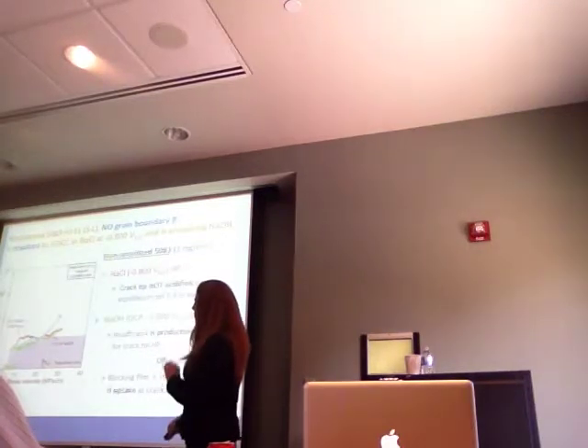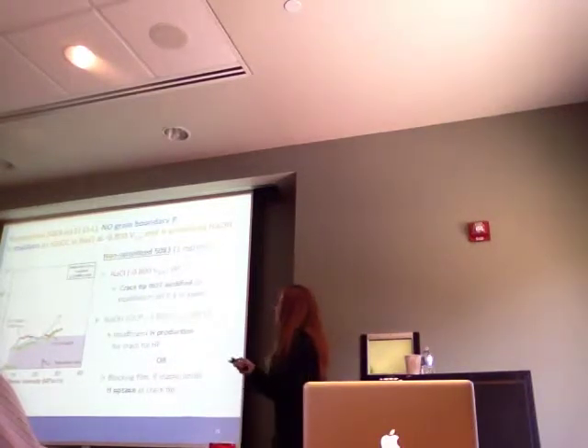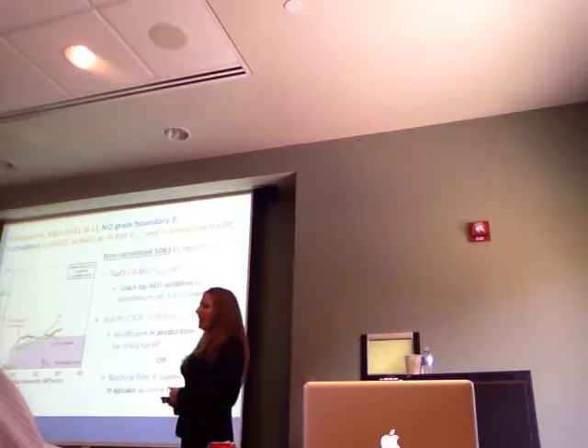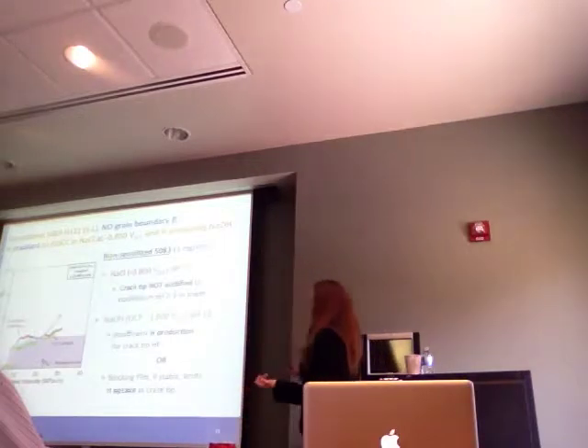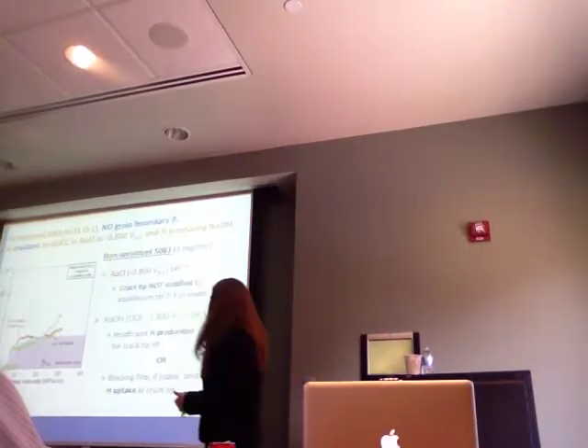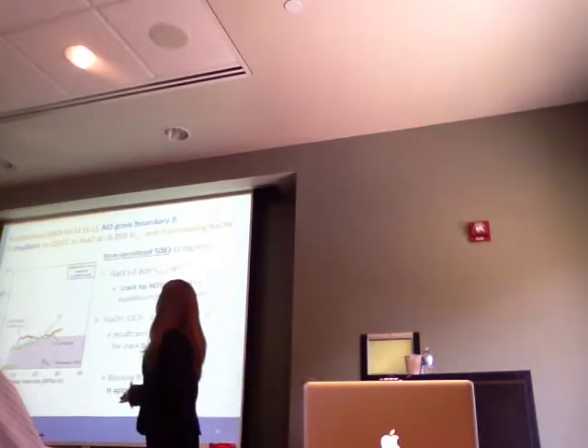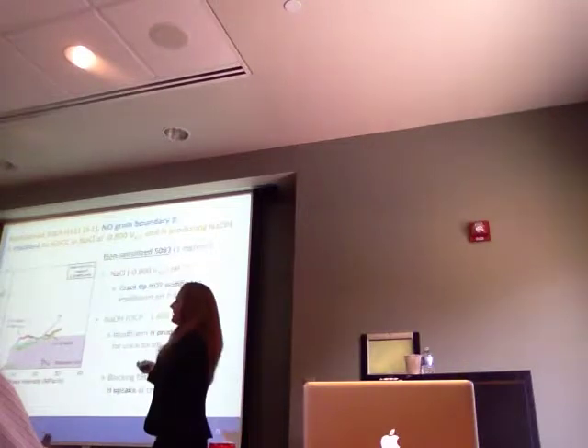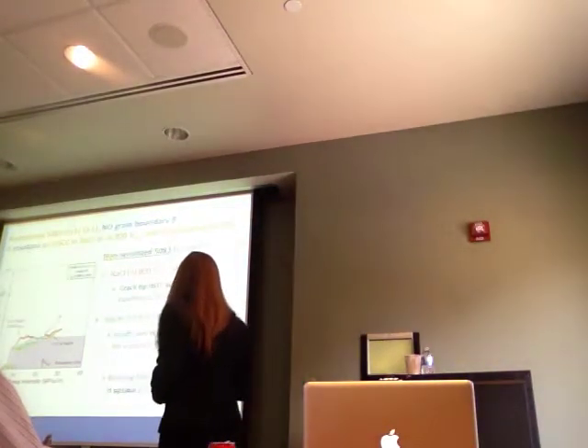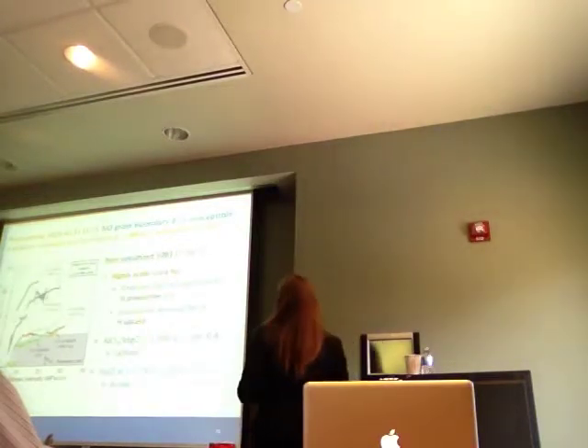These results are plotted here in green. There's actually 2 trends there. And both of these are, as you can see, very resistant to intergranular stress corrosion cracking. And this is likely because we're either not producing the hydrogen at the crack tip, or maybe there's something blocking the hydrogen from getting in at the crack tip. So we know that we need this acidic crack tip to cause embrittlement. So what can we do to make that acidic crack tip? Well, we came up with 2 different techniques to do this.